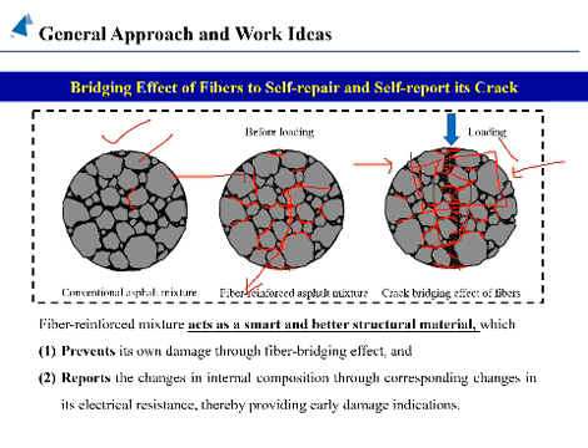We see that in pavement engineering, for example, this is the tire. There are basically two types: this is the tension, and this is basically the compression. For example, if the mixer is subjected to tensile loading, at the same time it is also subjected to compressive loading. In this stage, these fibers act like reinforcing materials. They reinforce the mixer within. So basically it acts like a smart and better structural material which prevents its own damage through the fiber bridging effect, and reports the change in its internal composition through corresponding changes in electrical resistance, thereby providing early damage identification, which was basically the problem.